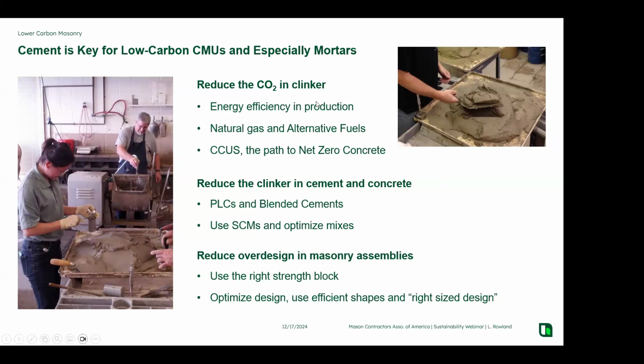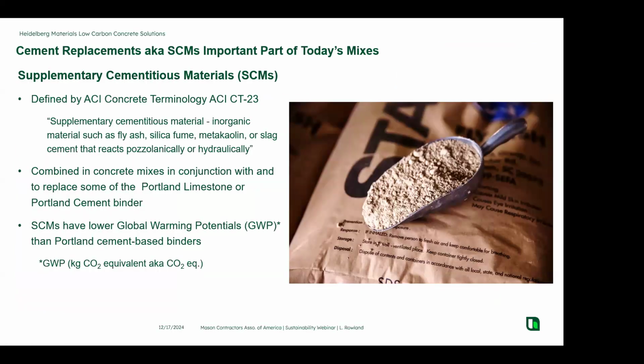So the way that we're going to reduce our carbon footprint in the cement is we're going to reduce the amount of clinker in our cements. We're going to be very energy efficient. We're going to utilize alternative fuels, etc. Ultimately, we have to use carbon capture, utilization, and storage because that's the only way to offset or essentially capture the CO2 associated with those process emissions, that calcination emissions. And then the other thing we're going to do, like we said, is reduce the clinker by producing blended cements, and also by utilizing supplementary cementitious materials. And of course, architects, designers, and folks that are working with masonry assemblies can also help tremendously by using the right block for the right block and brick applications, and then also, of course, using the right size design. No reason to put in a lot of extra materials that are unnecessary for the project.